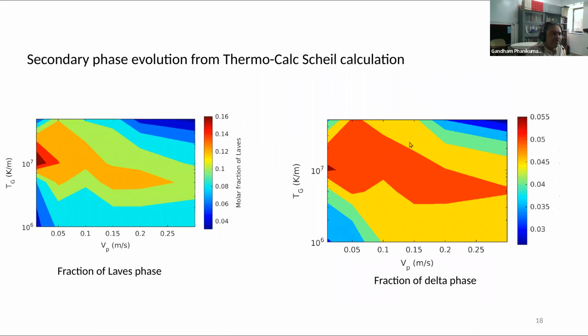So we refer to the so-called Thermo-Calc Scheil calculation, and as a function of temperature gradient and velocity, we go on to ask what would be the fraction of Laves phase formation and what would be the fraction of delta phase formation in Inconel. Now that actually shows you that there are some processing conditions where it is very high, and certain other processing conditions where it is very low or tolerable. Which means that you can tune the velocity of the heat source or the temperature gradient, which is via the powder bed heating, preheating of the powder bed. You can actually achieve the fraction of the detrimental phase to be under control. Now that's a very powerful idea.